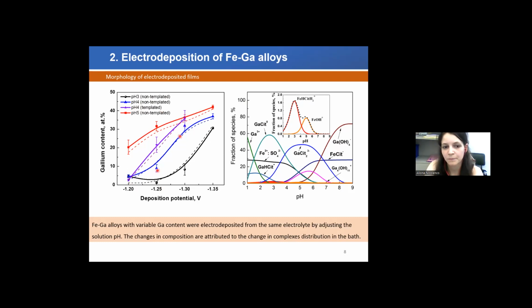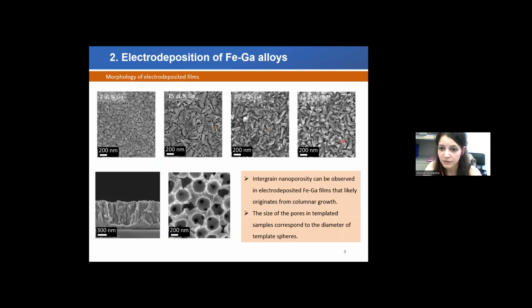So this again can be due to the alkalinization of the near electrode region that shifts slightly the equilibrium towards the formation of the gallium hydroxide species. And also we can suppose that the diffusion of iron citrate complexes may be hindered within the narrow channels of the porous colloidal template. So here is the morphology of the obtained films as a function of their composition. As you can see, it indeed changes significantly with the increased gallium content.